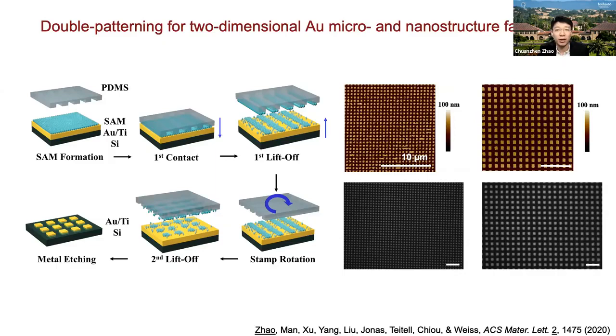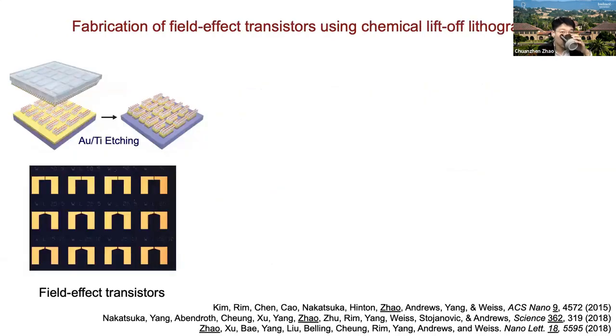The patterning process is shown on the left. After the first lift-off process, we clean the stamps and reactivate them. And after rotation of 90 degrees, we put them back on the previously patterned 1D surface for another lift-off process, which will generate the 2D gold nanoplasmonic structure arrays. Some AFM images and optical microscope images are shown on the right. As you can see, we were able to pattern highly uniform 2D gold nanostructure arrays with different features in large area. Those 2D gold nanoplasmonic structures can be used for plasmonic sensing, as I demonstrated previously for those 1D nanoribbons.